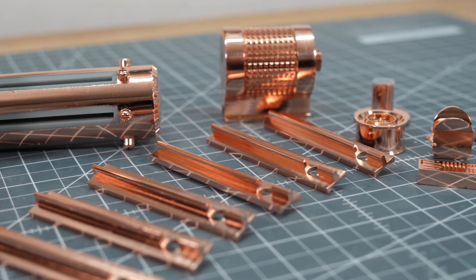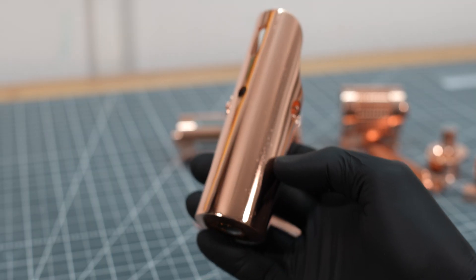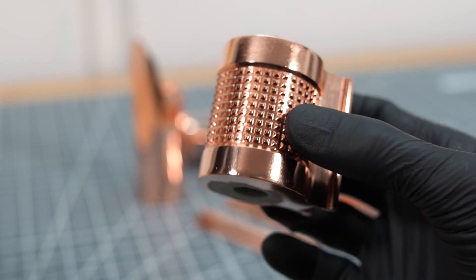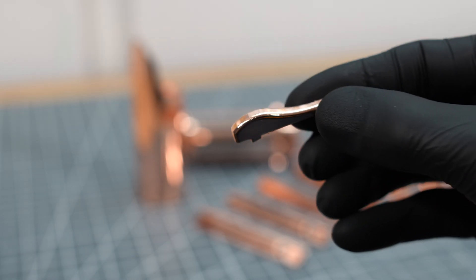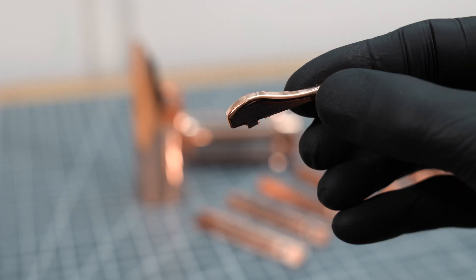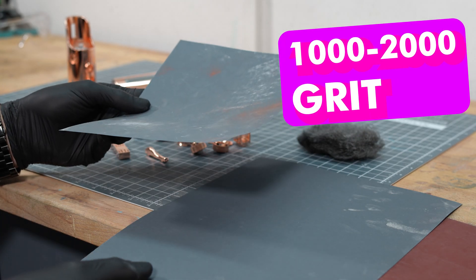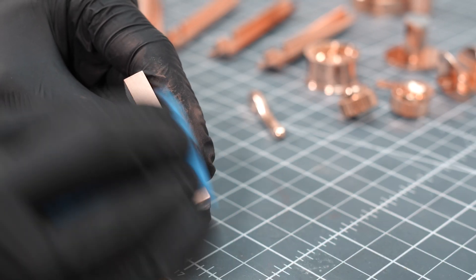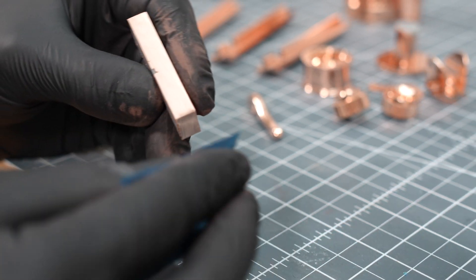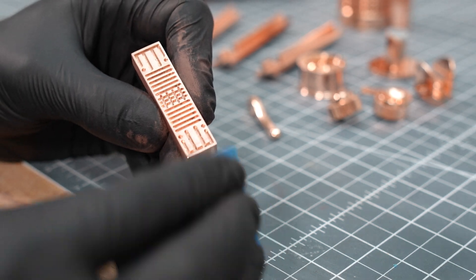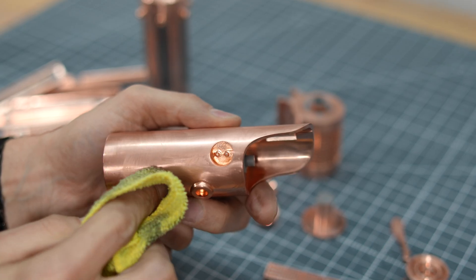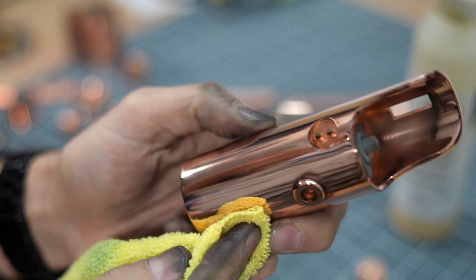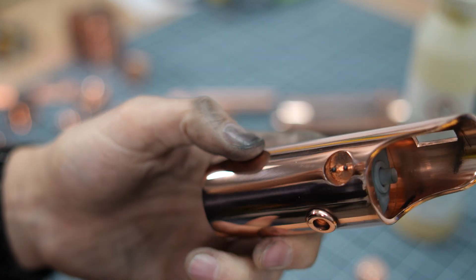Now the copper plated prints are sanded and polished. From my point of view, this is necessary to achieve this beautiful mirror effect. They already look good, but there are still some small, fine traces of impurities on almost all pieces. We will remove those. By the way, you can see here how insufficiently sanded areas can transfer onto the plating. For polishing, I use paper starting from 1000 grit and finish with polishing paste. The shine only unfolds completely at the end with this.